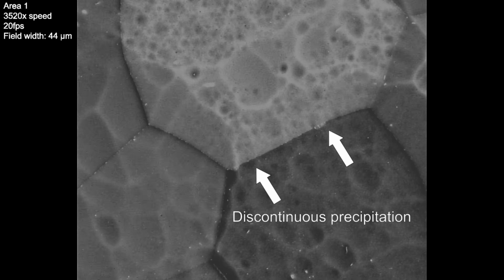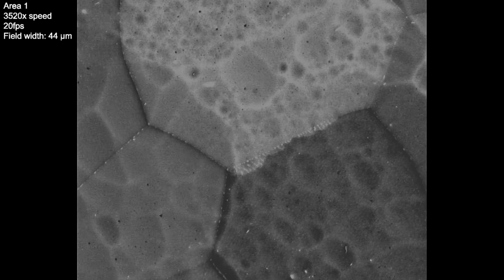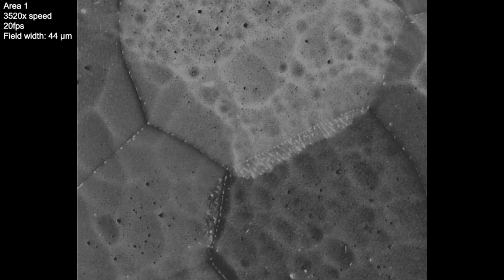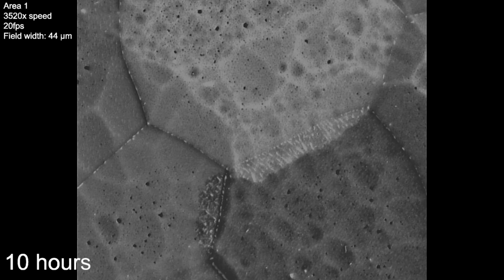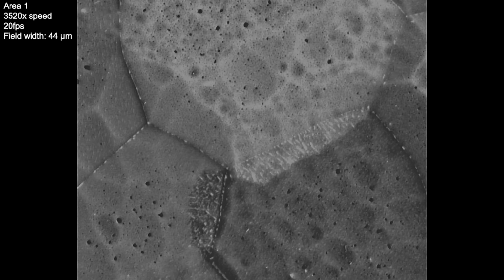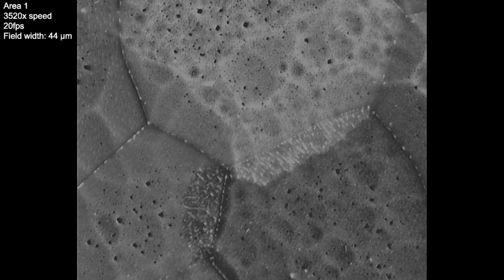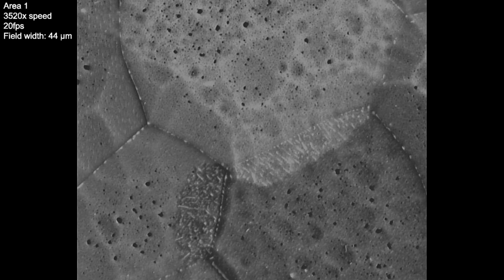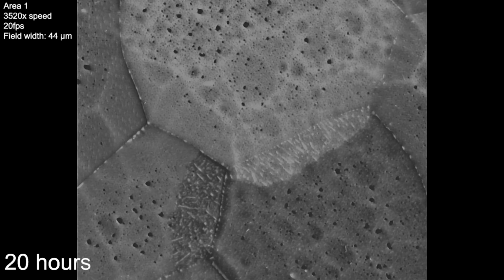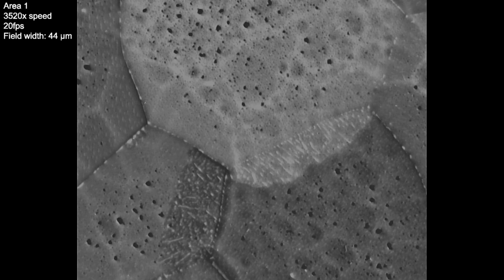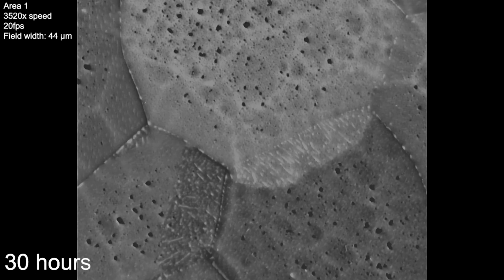In this section, you can see more clearly the stop-start motion of the discontinuous precipitation front, like it's getting pinned at various points in the microstructure. What is also clearer in this region is the grain growth that accompanies the discontinuous front. The backscatter electron imaging clearly picks out the crystal orientation difference between the grains with contrast, demonstrating the grain boundary is actually moving with the discontinuous front.